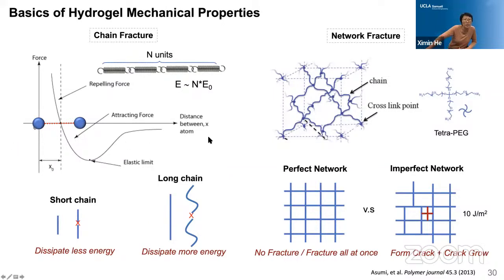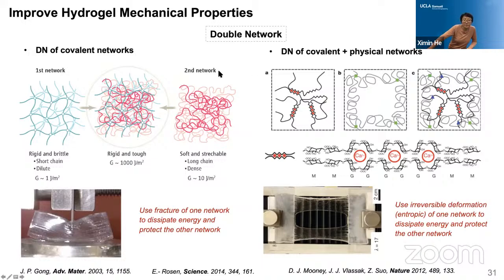And then a little bit of fundamental mechanics. So the overall polymer network's mechanical property is still determined by the basic chain fracture of a single chain. And we know through the theory, the longer chain can help dissipate more energy. And if you have a perfect network, then they can evenly distribute and share the load of the applied stress. However, this requires pretty special synthesis and monomers. And if there's any little defect in the network, the overall toughness of the gel network will fall back to the original low level of toughness.